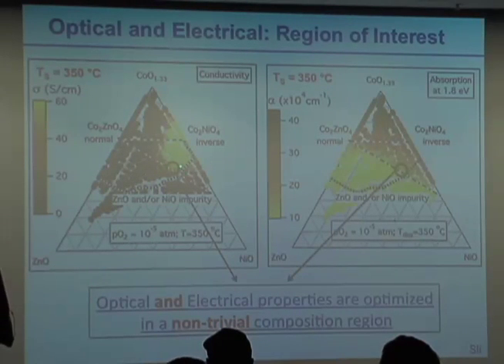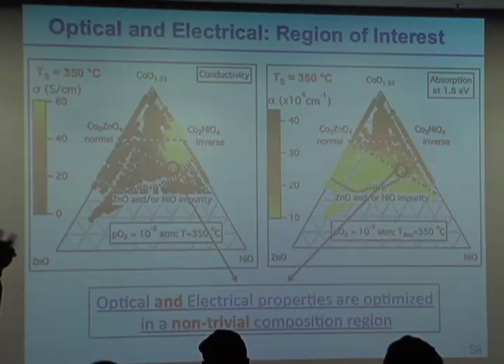We can do conductivity measurements here, and we can do absorption measurements here. And we can find regions where nickel doping increases the conductivity, and we see higher transparency than we do in either the normal or the inverse system. So we're able to now theoretically and experimentally explore this system, understand the doping in these spinels, and allow us to start the design.